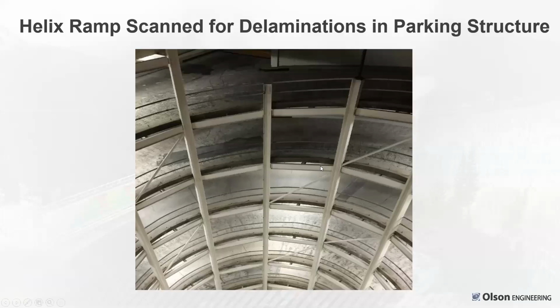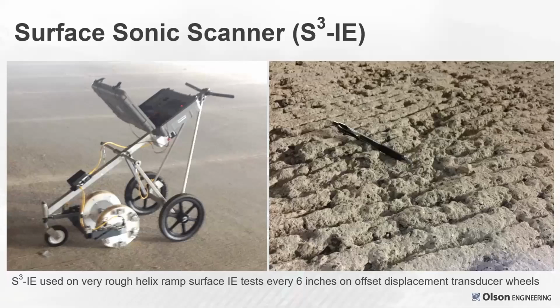So scanning was done down this ramp with our S-cube unit in concentric circles, rolling down the ramp, following a circular pattern. Again, this was our original S-cube unit. It rolls along on the same two wheels, just a different frame. And you can see how rough some areas of that surface were. This was very heavily degraded by some freeze-thaw damage, erosion, other factors. But we were able to still get very usable data.